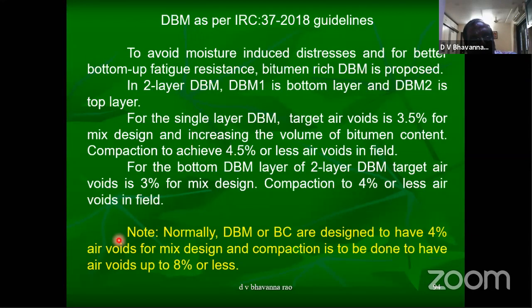But in every case, generally what we do is for DBM and BC, we design to have 4% air voids for mix design because the requirement of air voids is 3 to 5%. We will design for 4% air voids so that even with slight variation, the air voids will be in the range of 3 to 5%. And compaction is to be done to have air voids of 8% or less. Actually, we wanted the air voids to be 8% at the time of execution for bituminous concrete or the top DBM layers. But here they have changed it to 3.5 and 4.5, and 3 and 4% for the DBM layers. For bituminous concrete, we can adopt the usual one.